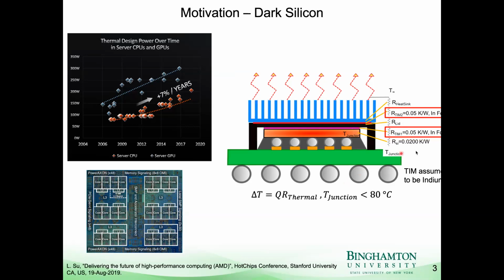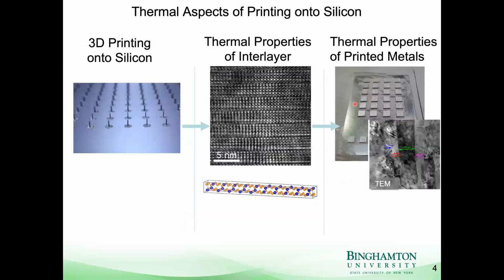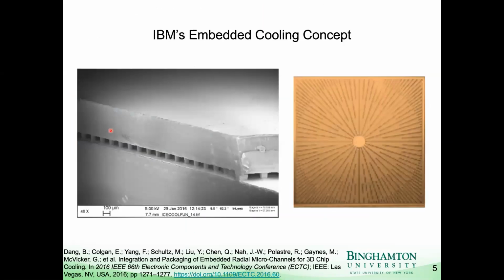So there's a big push to lower the resistance of the thermal interface material, and one proposed way to do that is going to be printing onto silicon. But before I go into that, I just want to maybe look at some motivation. A lot of researchers, especially in industry, have been looking at embedded cooling. This is a very promising technique from IBM, where they micromachine silicon microchannels. This is a top view of the design. They micromachine, using photolithography techniques, microchannels, and they basically have coolant flow through the center of this hole, and then that coolant boils as it flows radially outward from that center point. So this is a promising technique, but there are some limitations to this silicon micromachining technique.